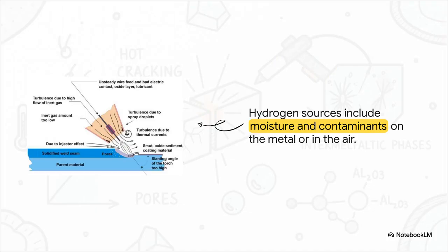And where's all this hydrogen coming from? Basically anywhere there's moisture. It can be humidity in the air, a little bit of oil or grease on the metal, or it can even be trapped in that nasty oxide layer we talked about at the beginning. This is why being obsessively clean is absolutely non-negotiable when you're welding aluminum.